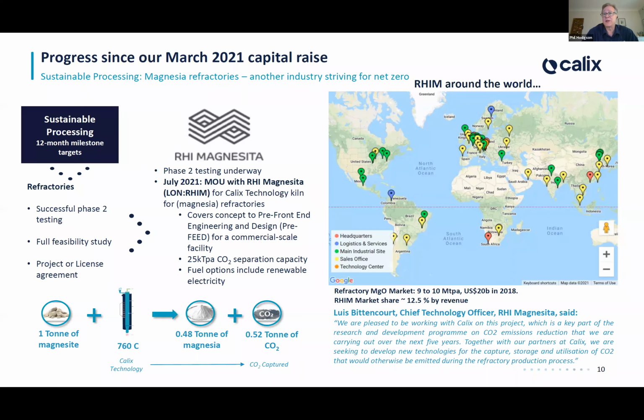And we've been working with RHI Magnesita for nearly 2 years now. And as I say, in July 21, we announced an MOU with RHI Magnesita to develop the first kiln into the refractory industry to capture that CO2 for them. And also, we're going to be looking at electrification of that facility, again, to take advantage of the fact that electrification of industry, the ability to use electrons, renewably generated electrons especially, in this process is of importance. This particular project looks at the initial stage, which we're in now, the front-end engineering design, what's called the pre-front-end engineering design or pre-feed, and it's for a commercial scale facility.